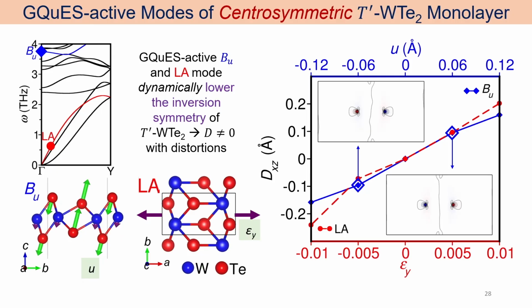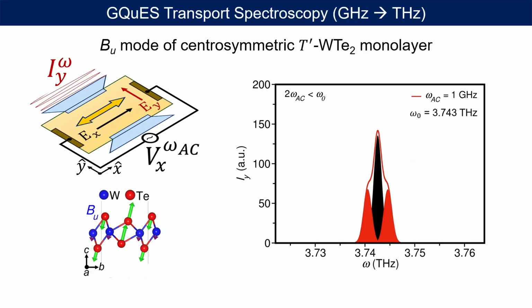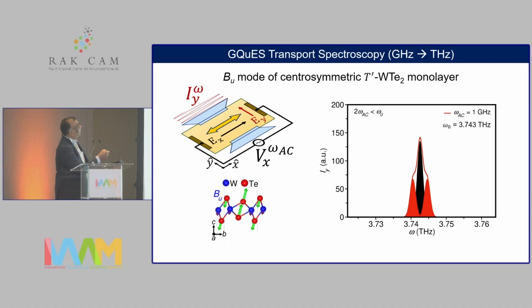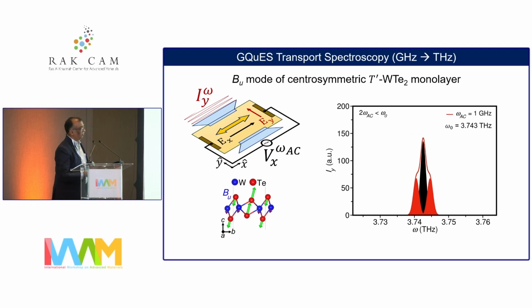Next is where you will consider centrosymmetric structure, where you don't have any Berry curvature or Berry curvature dipole. But even in this system, we show that using longitudinal as well as optical phonons, one can induce Berry curvature dipole, which is linearly proportional to vibrational amplitude, which means both of these phonons are active in the GQuES spectroscopy that we proposed here. And as a result, we predict that vibrational spectrum should be measurable if one measures Hall voltage or Hall emission from this sample.